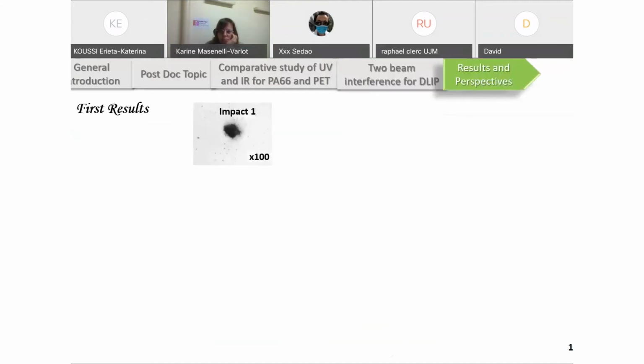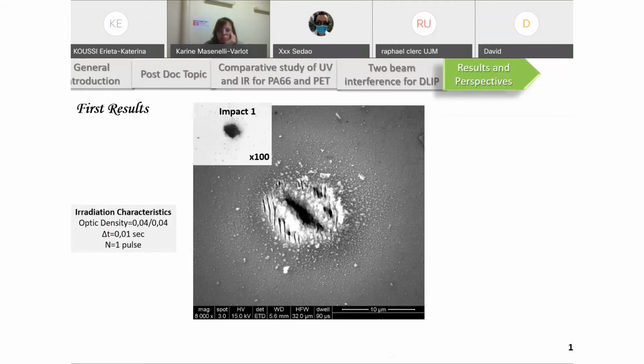So the first results after the illumination of the silicon illustrate the threshold impact imaged with an optical microscope. For this impact, we set the density filter to attenuate the laser energy as much as possible, and we minimized the duration of the shot as well as the number of shots. The first image, elaborated by SEM, reveals a primitive form of ripples with DLIP. As the DLIP period is proportional to laser wavelength and angle, we can intervene on the angle according to this formula and minimize the scale of the periodicity.